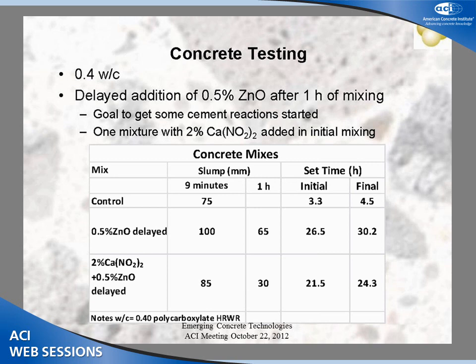As far as the concrete testing is concerned, concrete testing was conducted with concrete produced at a 0.4 water to cement ratio. In the case of this series of concrete tests, the zinc oxide was added as a delayed addition 1 hour after the mixing, and the whole purpose of doing that was to see if we could get some cement reactions initiated to get them started. A lot of things happen when you mix Portland cement and water, and a tremendous number of things can happen in the first hour. So the purpose was to try and get the cement reaction started, introduce the zinc oxide into the system, and see what happens from that point on.